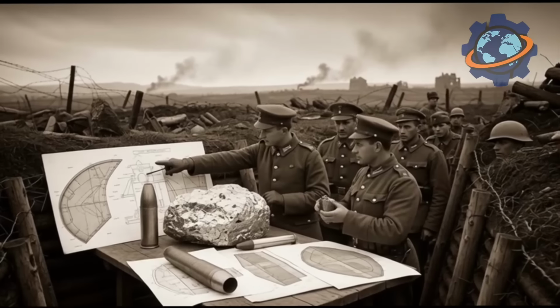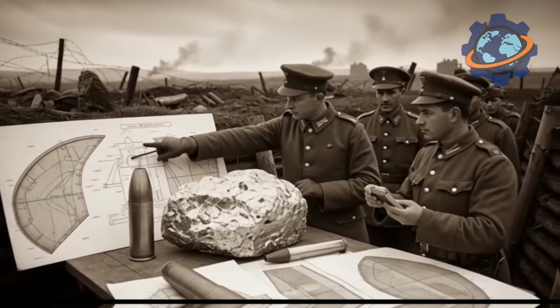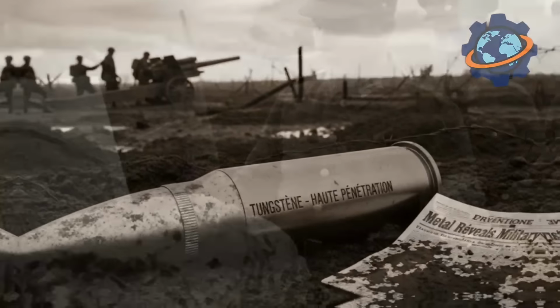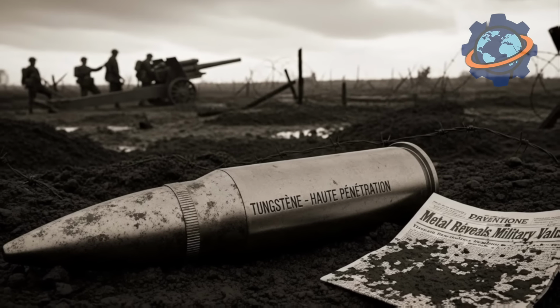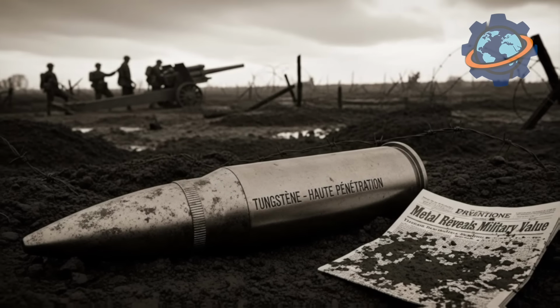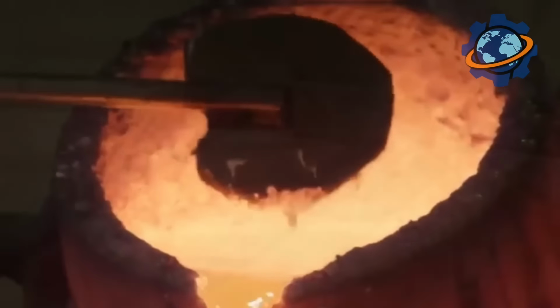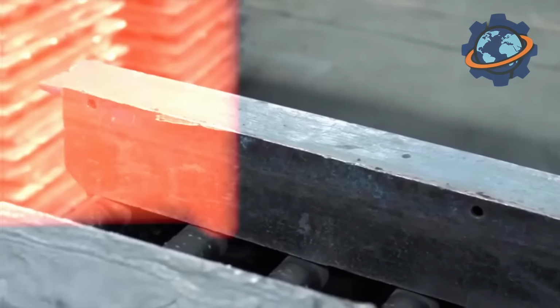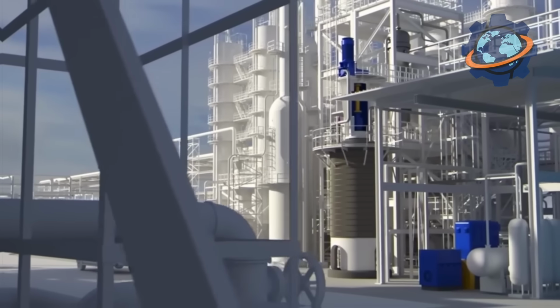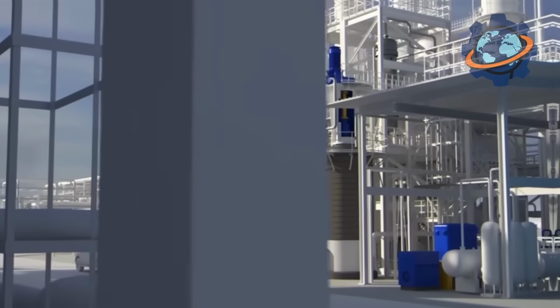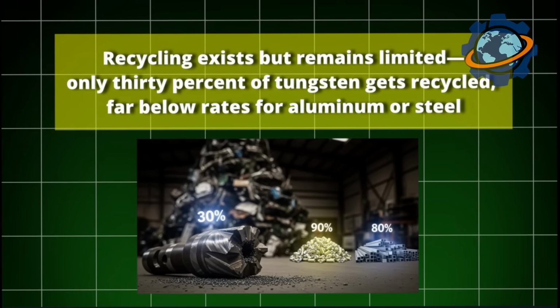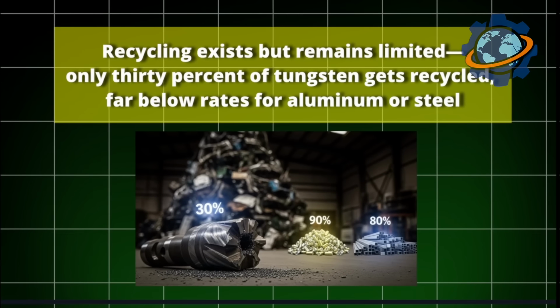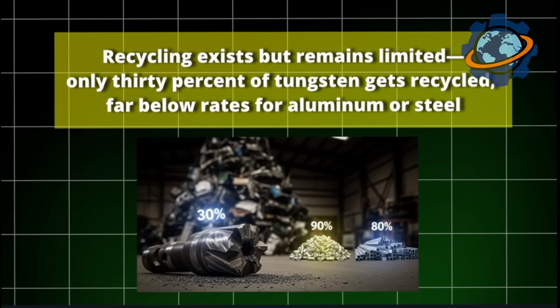World War I revealed tungsten's military value. High-speed steel cutting tools containing tungsten enabled mass production of weapons. Today's annual production exceeds 90,000 tons, with China dominating supply chains so completely that Western nations consider tungsten a strategic vulnerability. Carbon emissions remain problematic as tungsten production generates 8 tons of CO2 per ton of metal, primarily from energy-intensive processing. Recycling exists but remains limited. Only 30% of tungsten gets recycled, far below rates for aluminum or steel.